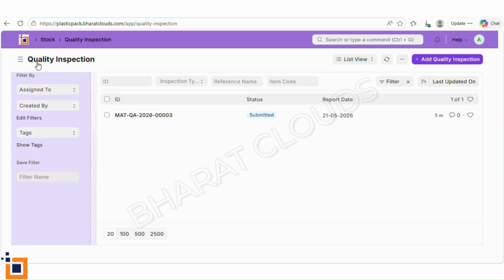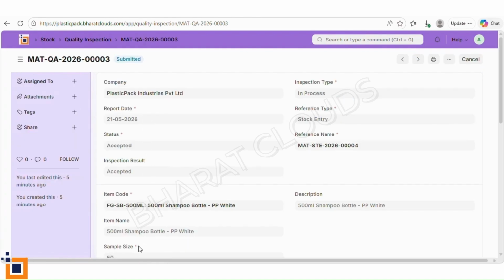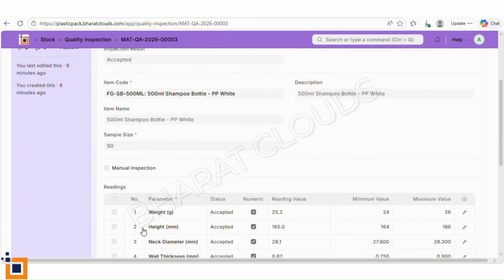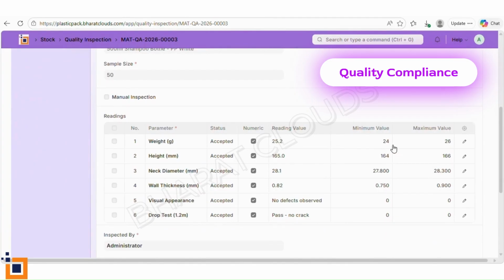Quality inspection. After production, before the goods leave your factory, they go through a formal quality inspection. A sample of 50 pieces pulled from the batch. 6 parameters tested. Weight, 25.2 grams, specification says 24 to 26. Pass. Height, 165 mm, spec says 164 to 166. Pass. Neck diameter, 28.1 mm, spec says 27.8 to 28.3.